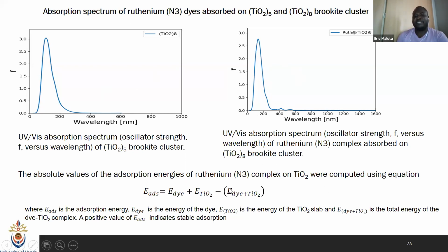And the other thing which we can calculate is the adsorption energy, just to indicate whether after adsorption our cluster is stable. And that gives us a way of showing whether we have improved the system we are looking at, by looking at the adsorption of the dye molecule on the surfaces of the Brookite, whether it's the Brookite bulk structure, the surfaces, or the nanoclusters, or any nanomaterials which we can think of.